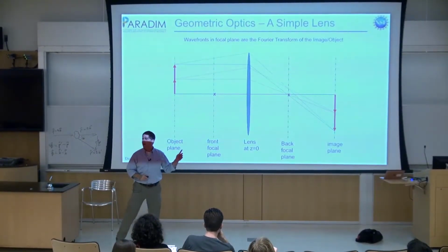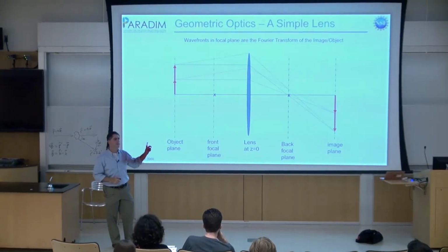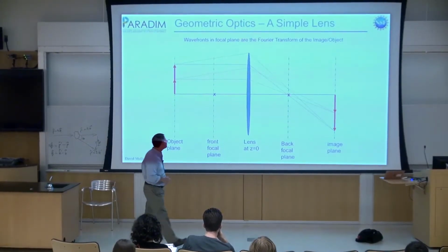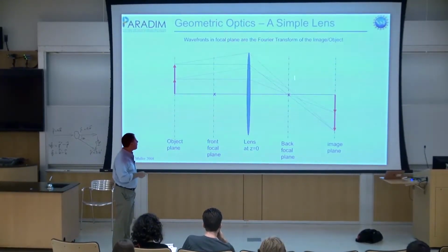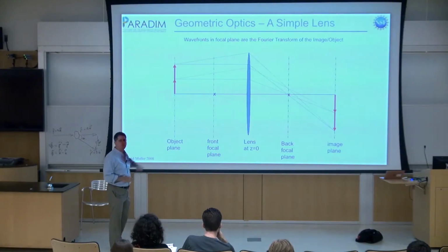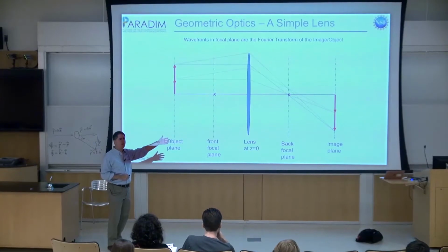So if I happen to put my detector in the back focal plane of the microscope, I have a momentum resolved detector. We're going to come back to that in the second lecture, and we're going to use momentum resolved detectors to measure probability current flow. What I want you to remember for now is the microscope has a very convenient way of doing Fourier transforms for us, which is simply switching to diffraction mode, and you get to see the square of the Fourier transform, because remember, when I look at a wave function, I don't see the wave function, I see psi squared and not psi.